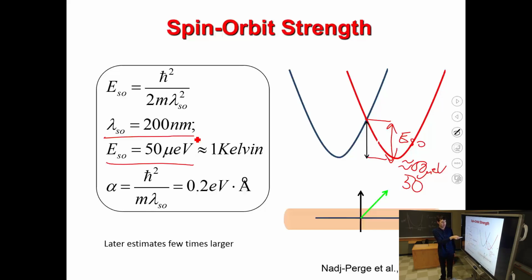If you plug in a larger number, it will shrink more and more. It can become 100 or 50 or 10 nanometers. Then you compare this to the length of the nanowire, which is a couple of microns. And this is at least a factor of 10 smaller than the nanowire length. So this is a good spin-orbit strength, a good ingredient for our Majorana recipe.